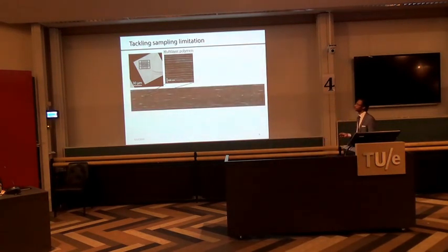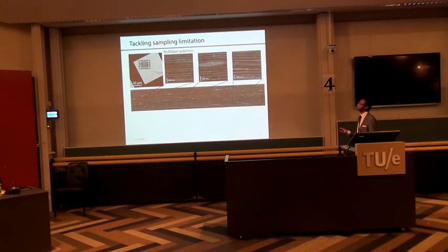For instance, in this case, we can see a typical multi-layer polymer sample, with the HDPE layer and PP layer arranged perfectly with a regular spacing. However, on a large-scale map, we can also see the flow defects. We can also see the irregularity in the spacing.